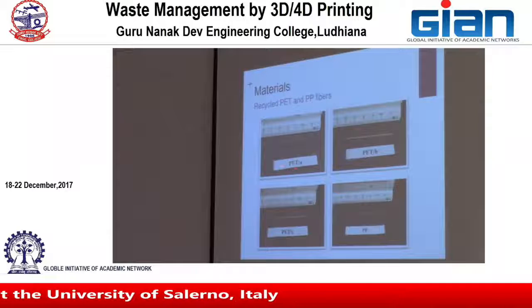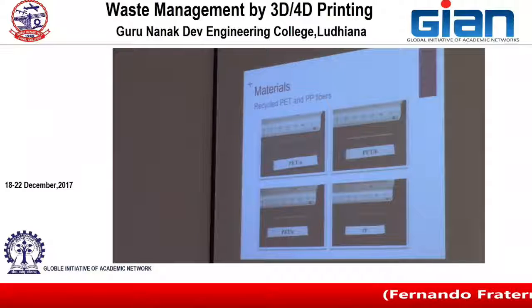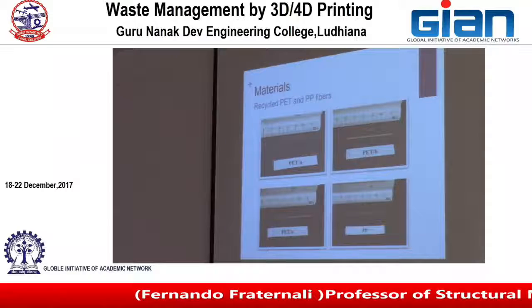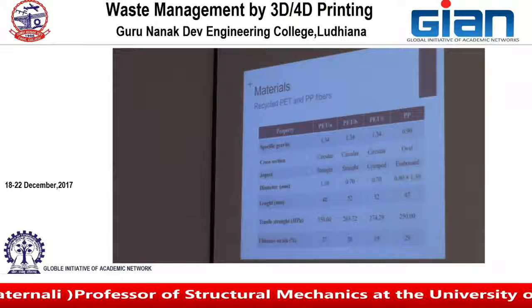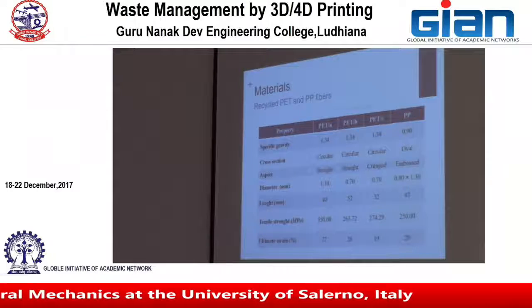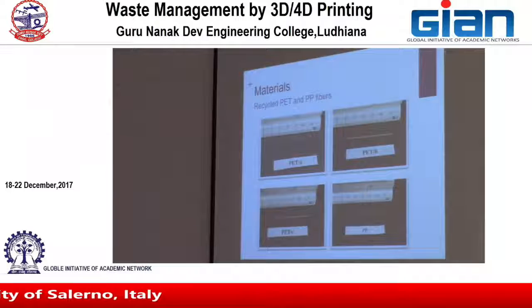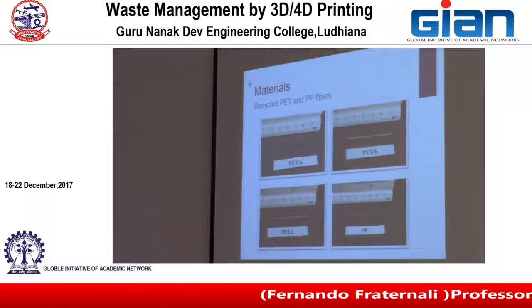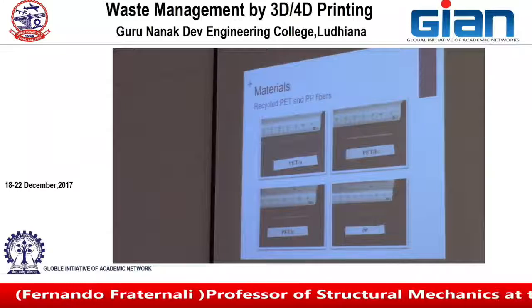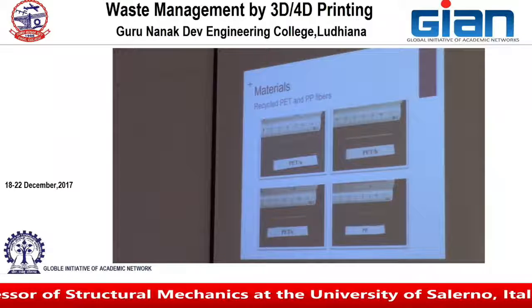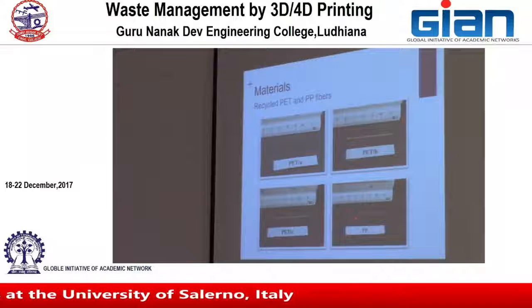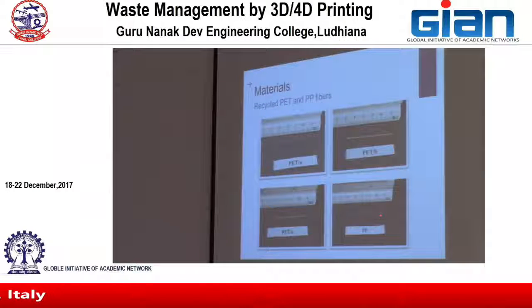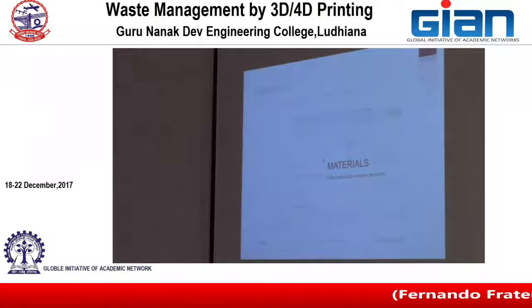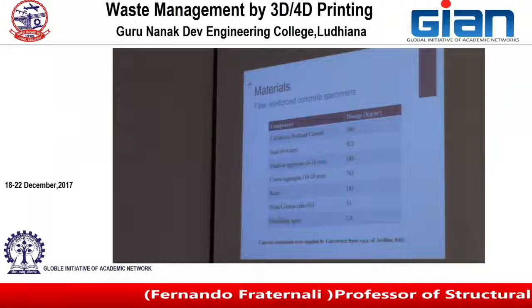PETa are straight fibers, high strength straight fibers. PETB are again straight fibers with considerably lower tensile strength. PETC were crimped fibers. All those fibers were made of recycled PET. And finally, we had some PP fibers which show embossments on the lateral surface. Then we mixed those fibers into a concrete.